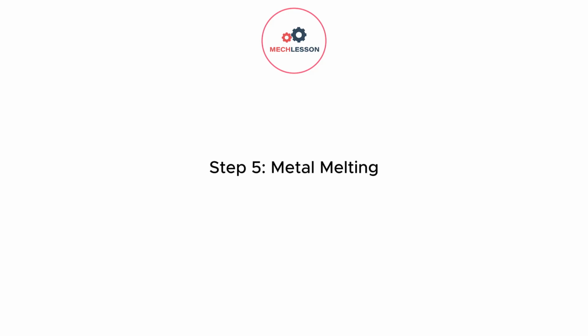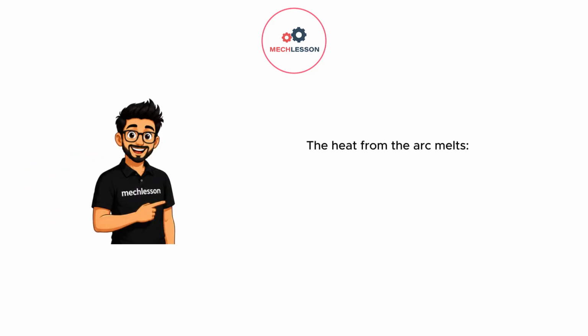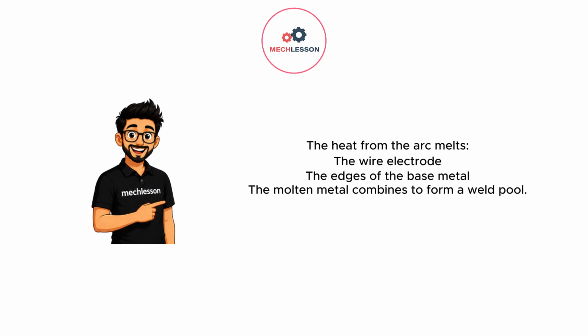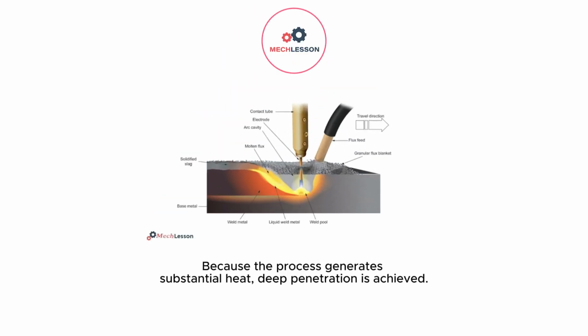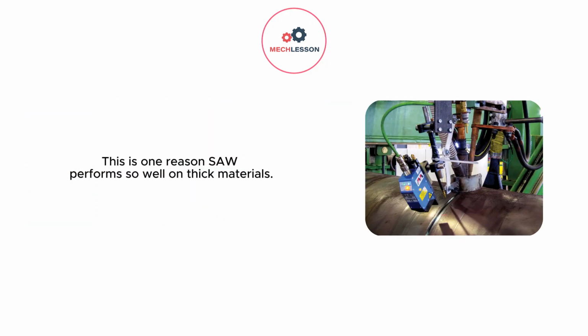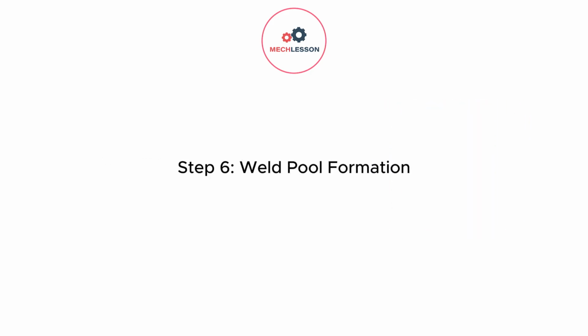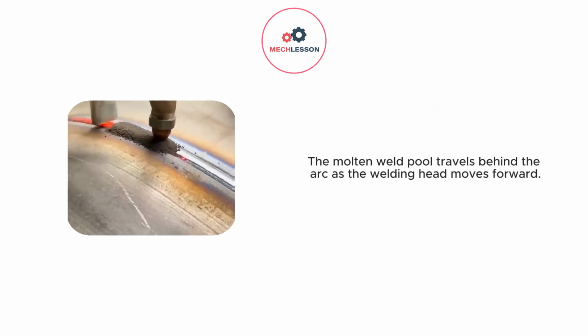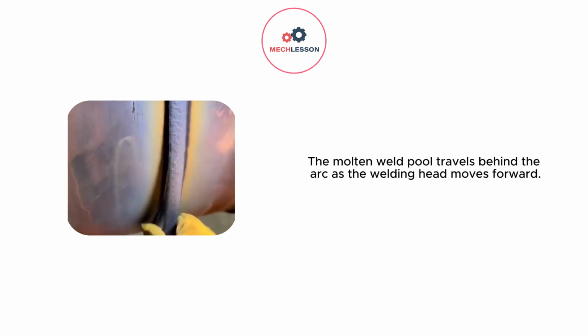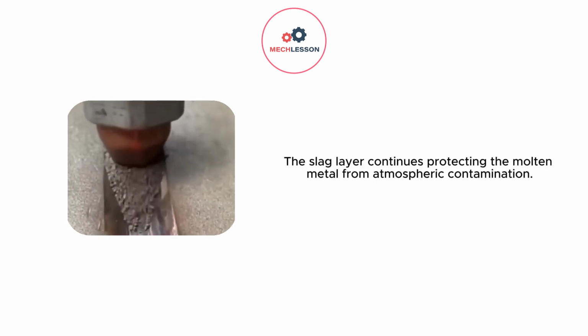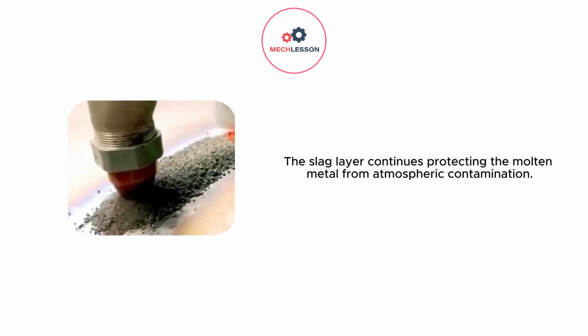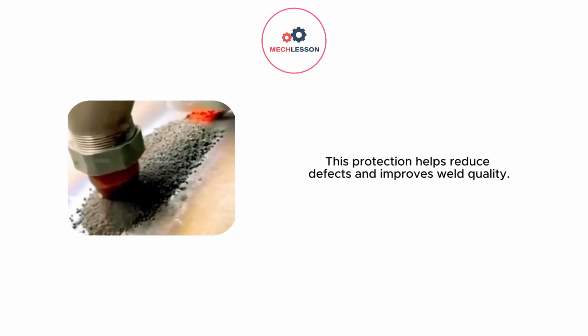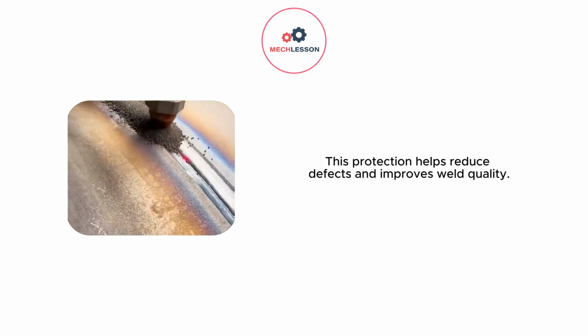Step 5. Metal melting. The heat from the arc melts the wire electrode and the edges of the base metal, and the molten metal combines to form a weld pool. Because the process generates substantial heat, deep penetration is achieved. This is one reason SAW performs so well on thick materials. Step 6. Weld pool formation. The molten weld pool travels behind the arc as the welding head moves forward. The slag layer continues protecting the molten metal from atmospheric contamination. This protection helps reduce defects and improves weld quality.